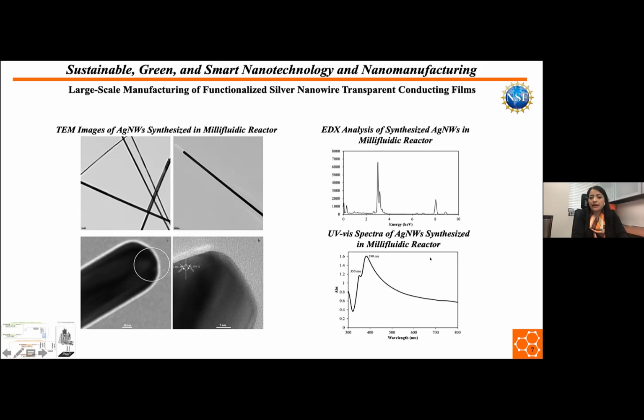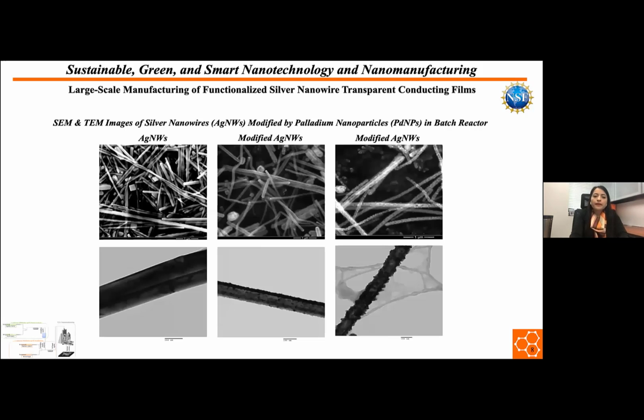As you can see, we have 2 peaks which correspond to silver nanowires, and the peak around 420, which corresponds to silver nanoparticles, has totally disappeared, which means that we are producing purely silver nanowires without any other nanostructures as byproduct. So far, we are able to produce silver nanowires with high aspect ratio and well-controlled in the millifluidic reactor.